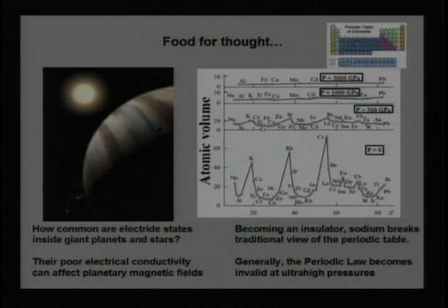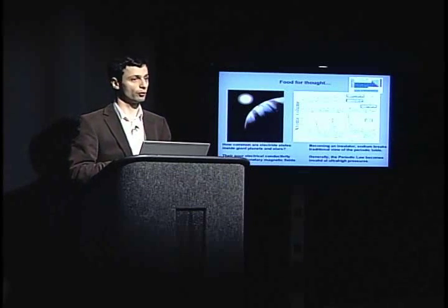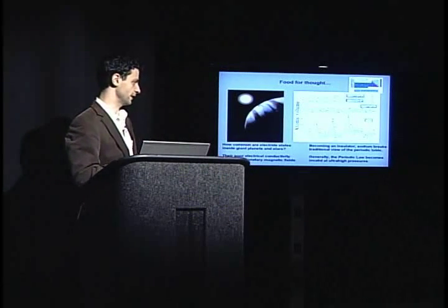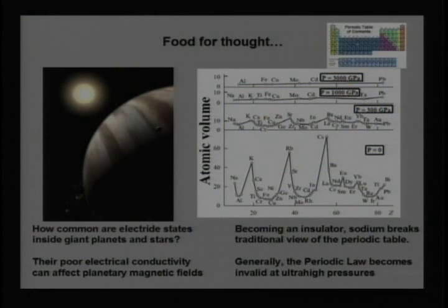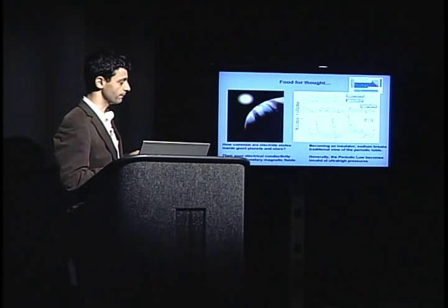This can be observable because magnetic fields of planets and stars are generated by convective motion of electrically conducting liquids in the interior of the planet. Now, if the liquid is no longer electrically conducting, if it's an electride state, then you will probably notice it through the weakening of the magnetic field. Furthermore, the very fact that sodium, an archetypal alkali metal, becomes non-metallic under pressure challenges the validity of the periodic law of the periodic system at ultra-high pressures. This may sound shocking, but in a way we knew it before. This is just yet another illustration of this phenomenon.